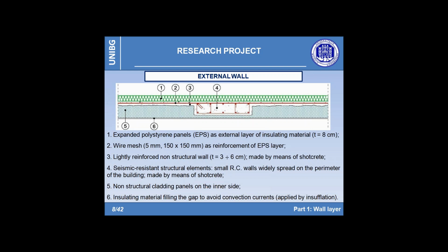The last phase of each floor construction consists in the cast of the upper two-way slab, and so no beams or drop panels are required by the system, thus ensuring the maximum ease and construction speed. After casting of the shotcrete for the structural wall, and if this is the case for a lightly reinforced non-structural panel, the wall section is finally completed by placing cladding panels on the inner side and by filling the inner chamber with proper insulating material, thus improving the thermal and acoustic efficiency of the construction system.